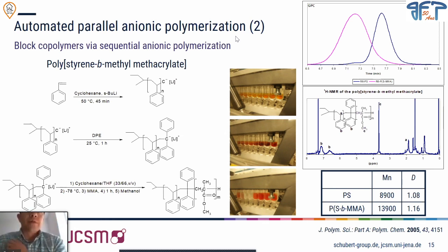anionic polymerization is a nice technique to build block polymers, because basically under good conditions of inertization, the polymer is always living, you know, so you can keep adding different monomers and grow some block polymers, right? So we picked this example because then you have to go very low in temperature. We wanted to test the machine, how far you can go.